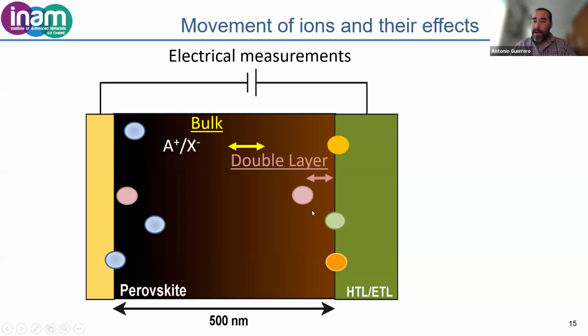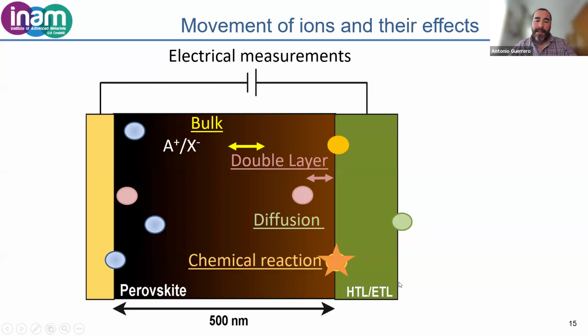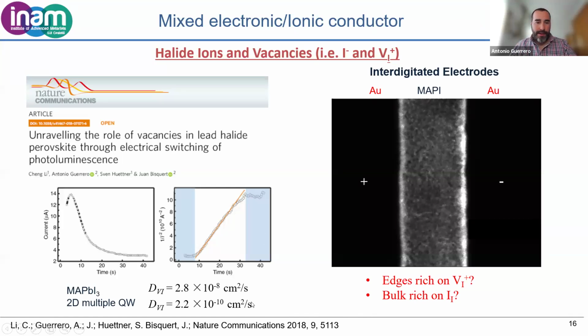So this double layer capacitance that we are able to observe is typical of electrochemistry. So the perovskite is behaving as if it was a liquid, meaning that the ion migration inside the perovskite is very fast. And then the ions, once they reach the contacts, can diffuse through these hole transport layers or electron transport layers. And in some cases, they can also give rise to chemical reactions. Here I show you one example in which we characterize the ion migration of this type of perovskite formulations. In this experiment, we place a methyl ammonium lead iodide perovskite on an interdigitated electrode.